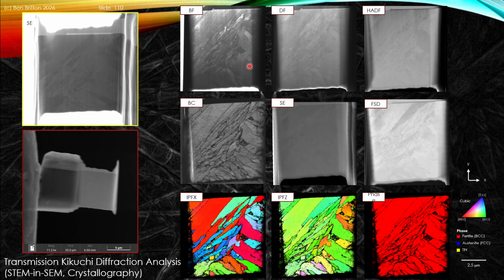We can also do more traditional STEM imaging, so we have a STEM in SEM detector on our Amber X instrument, so you can do bright field, dark field and HAADF to reveal the different microstructural regions as presented here. Importantly, the bright field, dark field and HAADF are with respect to the through thickness attenuation and scattering contrast. The TKD data is from the bottom surface of the foil. So it's typically the very near surface, and so that's where the final polishing steps at low kV are very important in this example.